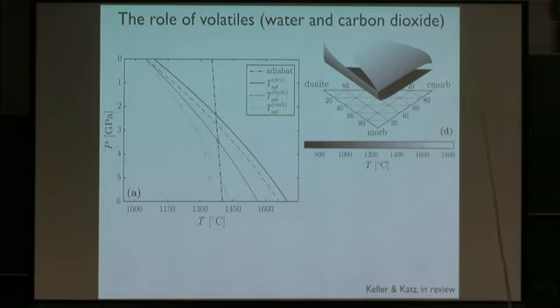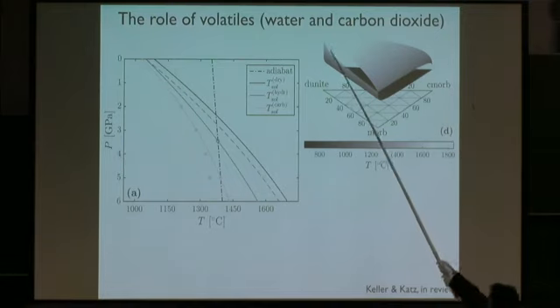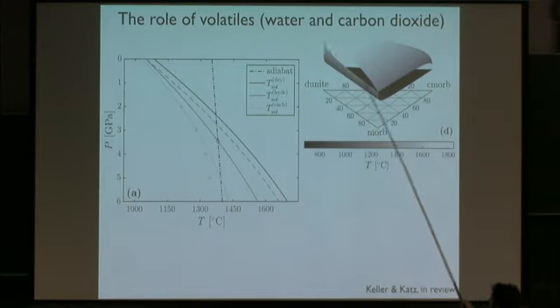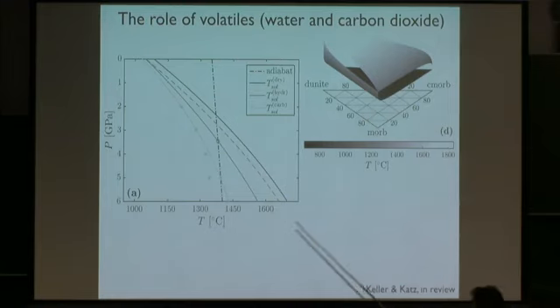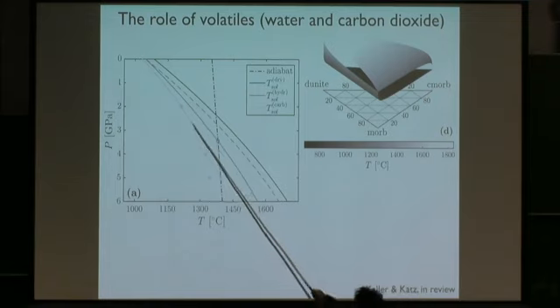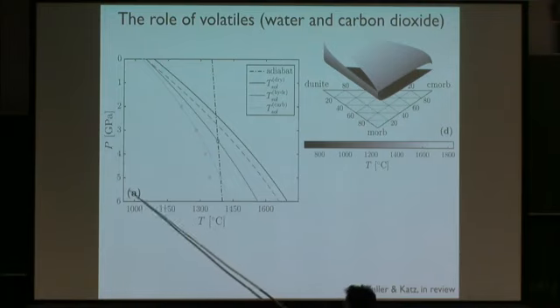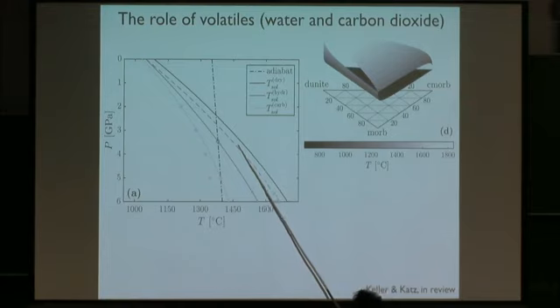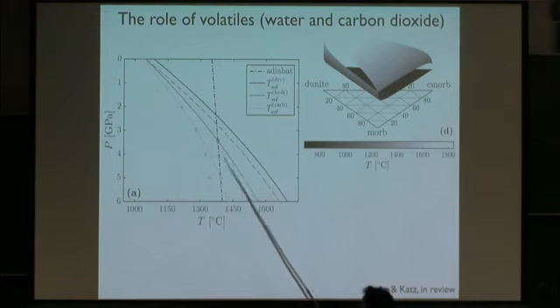So instead of just dealing with carbon as an end member, which has extreme behavior, we do something a bit more moderate. And what you can see is the solidus steps down from dunite to MORB, and it steps down again as you go to this carbon-rich MORB. This phase diagram allows you to calculate the solidus and liquidus anywhere in this 3-component space. So for 100 ppm of water, this is what you get. There's the carbonated solidus as a function of depth, the hydrated solidus, and the dry solidus, and I actually can't remember what that line is. But here's a typical adiabat.